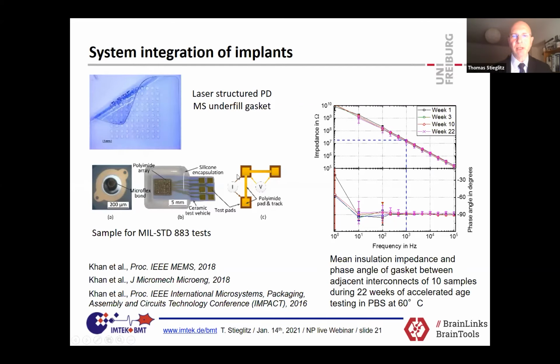And then we measured adjacent contact pins with a distance of, I have to lie somewhat, a little bit below 1 millimeter. And after 22 weeks at 60 degrees C in saline solution, we still got about 20 megaohm at 1 kilohertz insulation resistance. That means this could be an option, combining old school silicone rubber technology with micromachining to approach those challenges of assembly.